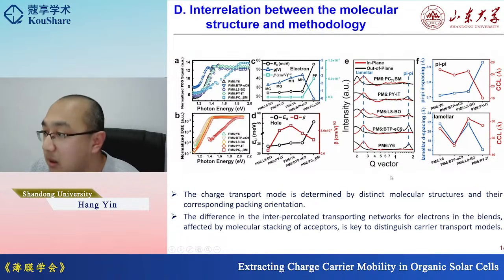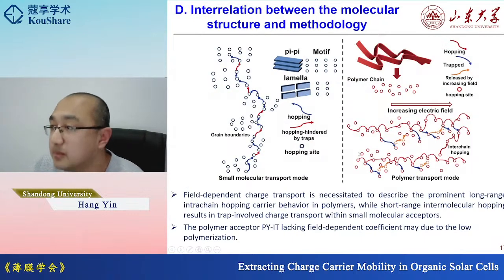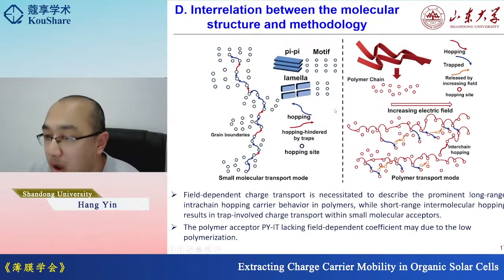We can see here the difference in the inter-percolated transporting networks for electrons in the blends affected by molecular stacking of acceptors is key to distinguish charge carrier transport models. And then we just observe the field-dependent charge transport is necessary to describe the prominent long-range intra-chain hopping carrier behavior in polymers. In polymers, we always get the field-dependent Poole-Frenkel effect, whereas on the other side, the short-range intermolecular hopping will usually result in the trap-involved charge transport model with the small molecular acceptors, just like the pi-pi stacking.